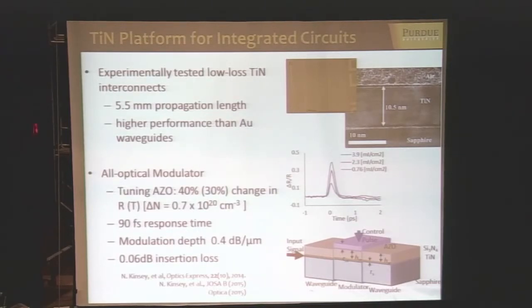When you combine it with titanium nitride waveguide, you could have this modulator which has really good properties. You can change, in this case, the charge carrier density by roughly 10 to the 20 per cubic centimeter - it's quite significant change.